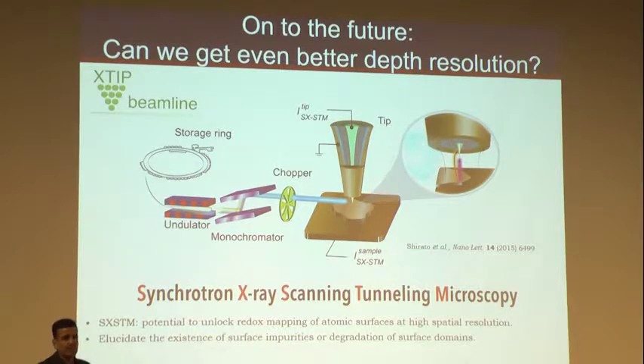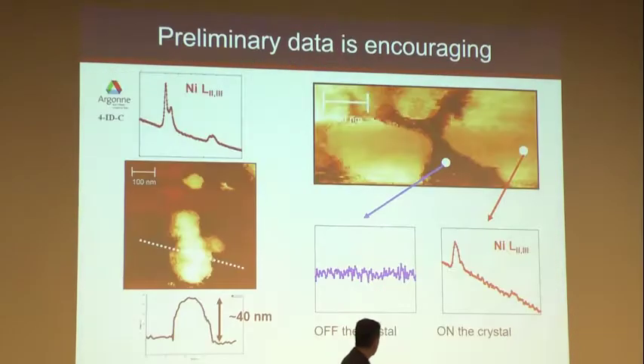And so the idea here is that you're getting much more sensitive information, but you're still able to map a particle, or at least that's our hope. This is data from last week, was it last week that we measured this? So this is really, really recent. But the idea here is to show that we're able to get nickel data.